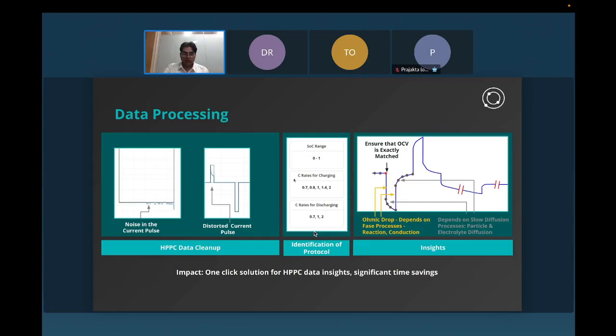Now, we first of all clean up all these things, like I mentioned earlier. After cleaning up, we identify the protocols. Like HPPC test was conducted in what SOC range, whether it was changed from 1 to 0 or 0 to 1, or both charge and discharge portions were present. What were the C rates for these pulses? What were the C rate for discharge pulses? All of that gets automatically identified. And of course, we have identified all these pulse regions, we have marked them so that this is now ready for running the optimizations.